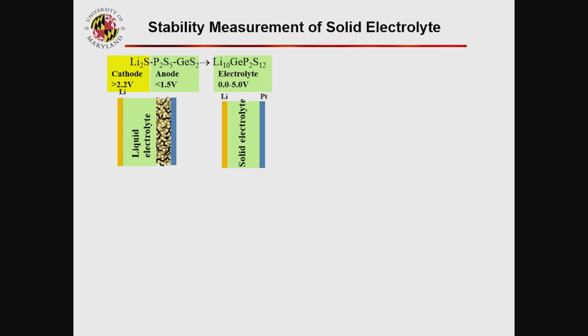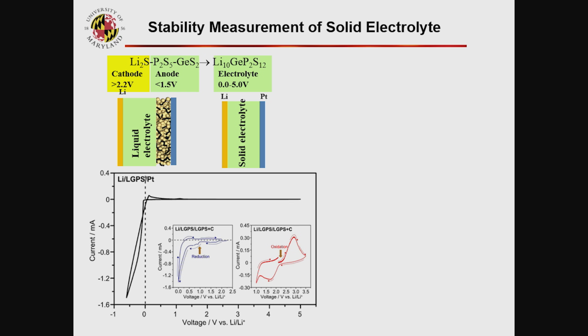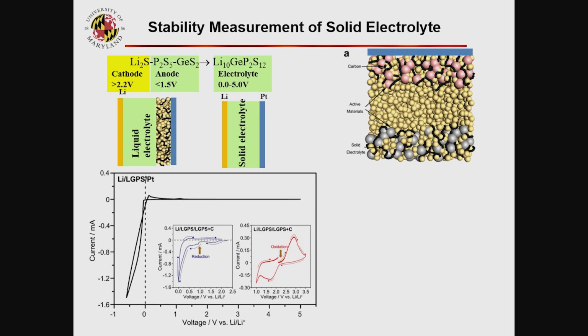Here we think there is still a reaction between the electrolyte and the Pt, but the surface is too small, and your scan rate is faster, so the current is too small to be detected. But in the real case, in a battery, you really have a lot of carbon there. So this case is not the same as the real bulk battery. But this case is the same as a thin film battery. The thin film battery we develop right now is an all-solid-state thin film battery, no problem. But if you want to build a bulk electrode, you have a lot of carbon there. So you have to use a different technology to measure the intrinsic stability. This technology right now is only suitable for thin film batteries.